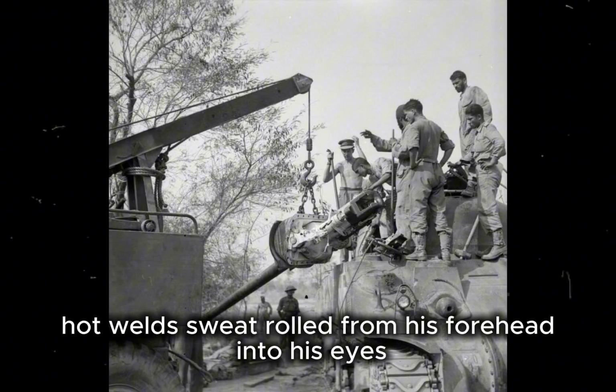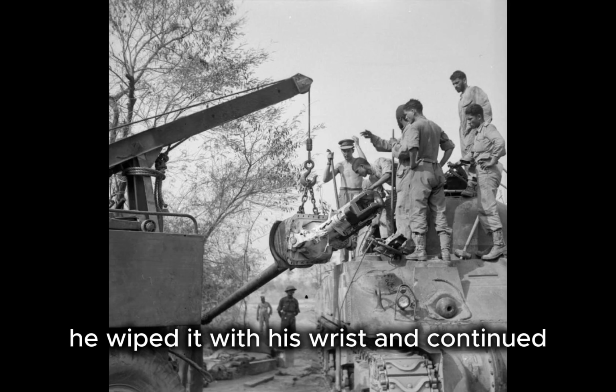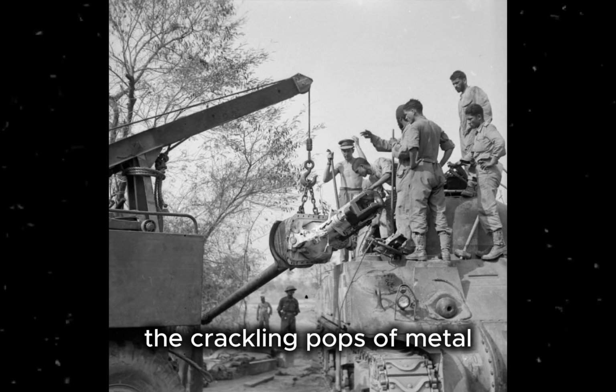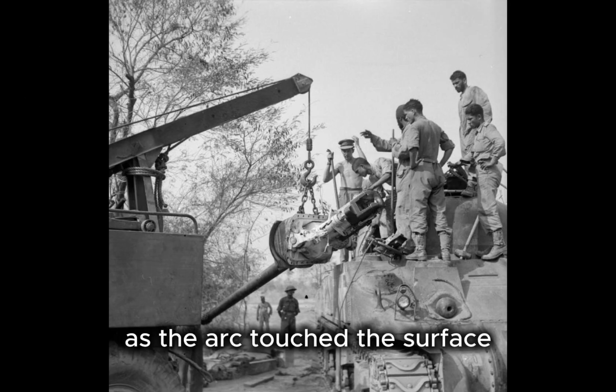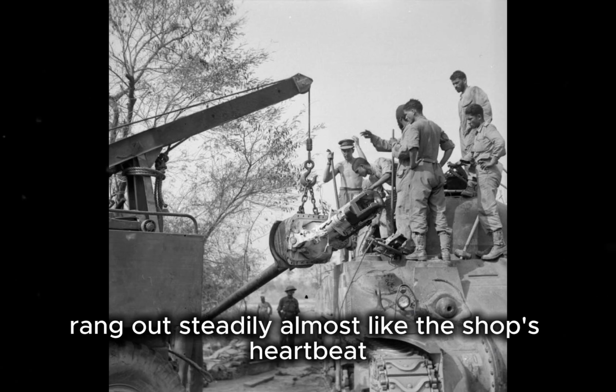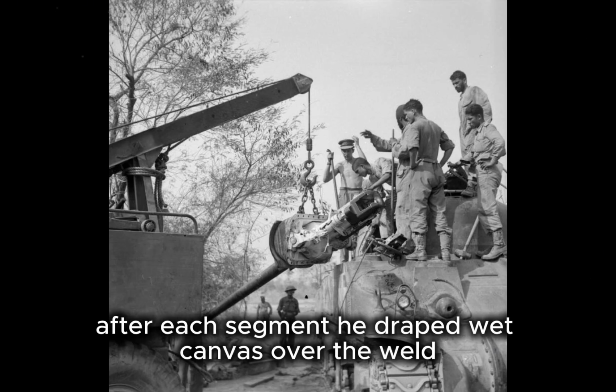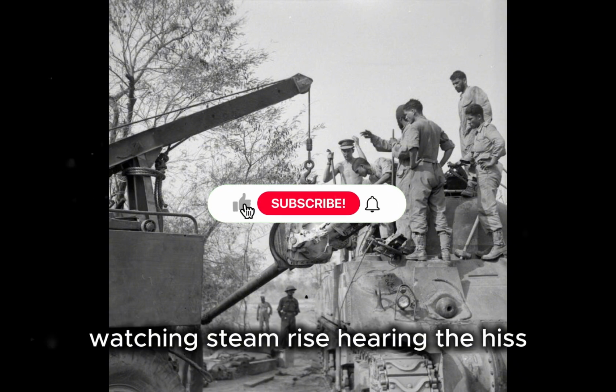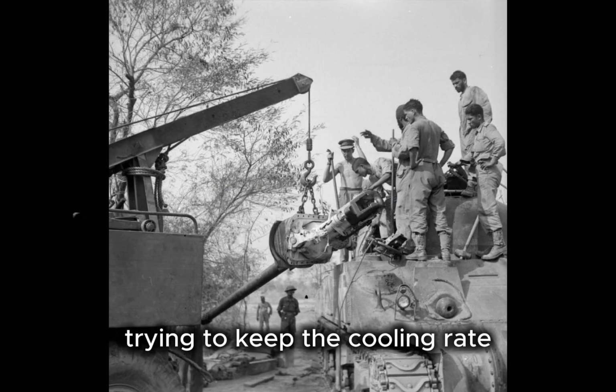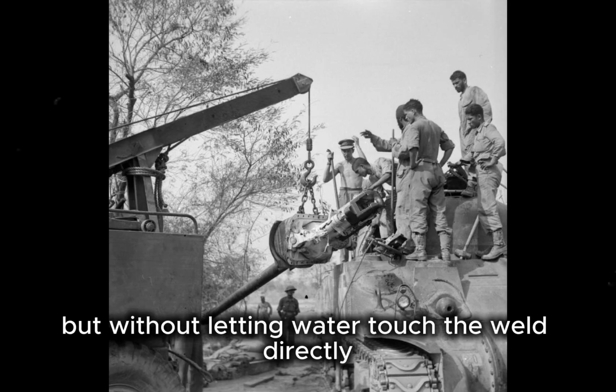Sweat rolled from his forehead into his eyes. He wiped it with his wrist and continued. The crackling pops of metal as the arc touched the surface rang out steadily, almost like the shop's heartbeat. After each segment, he draped wet canvas over the weld, watching steam rise, hearing the hiss like the steady breathing of cooling steel. Where needed, he used a heat gauge to ensure the surface did not cool too quickly, trying to keep the cooling rate slower than industrial standard, but without letting water touch the weld directly.